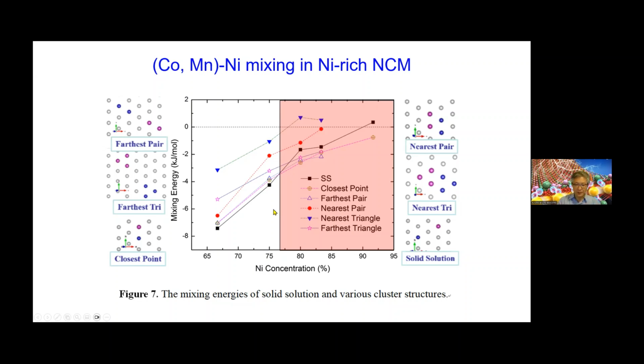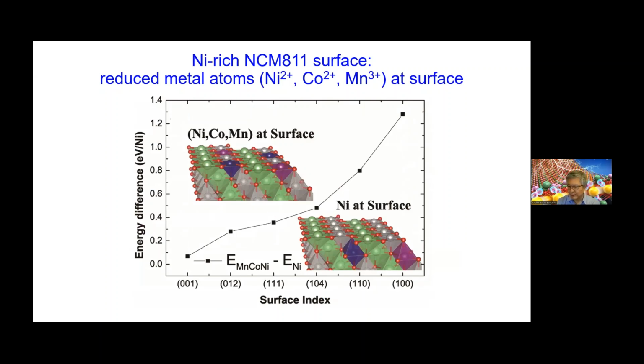So here are the actual practical issues we have addressed. When we make the material, of course, everything is finite, so there is a finite typical size of the cathode material particle, 5 to 10 micron. There are surfaces. The typical NCM cathode material surface is supposed to have the corresponding elemental ratio, but if you compare that with a pure nickel oxide surface, the nickel oxide surface is more stable than the NCM mixed metal surface, leading to a surface that will be nickel-rich.